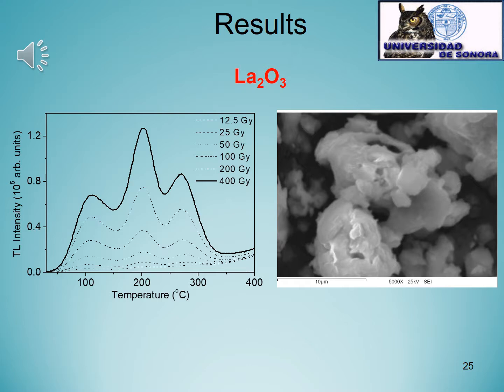We can observe the sintering process for the particles on the SEM image at the right, which is a very desirable property for the morphology in terms of particle size, for tuning or modifying the TL signal.